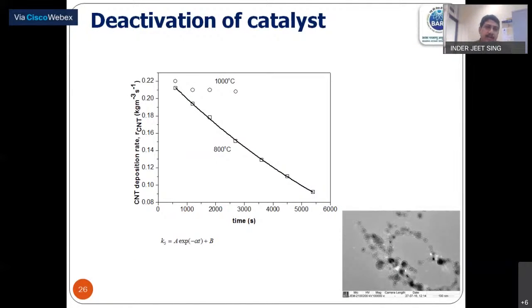Now, as I was talking about deactivation, we could find how the reaction rate changes with time, and that can also be put in a mathematical model. So the rate constant can be expressed in this equation, from which you can get the value of the constant. And I am showing one TEM image where, once the catalyst is deactivated, basically what happens is they are covered with unwanted forms of carbon. Once the catalysts are covered, they cannot nucleate the CNT. You can see somewhere small CNTs have grown, but finally once it is covered, you cannot see further growth of CNT.